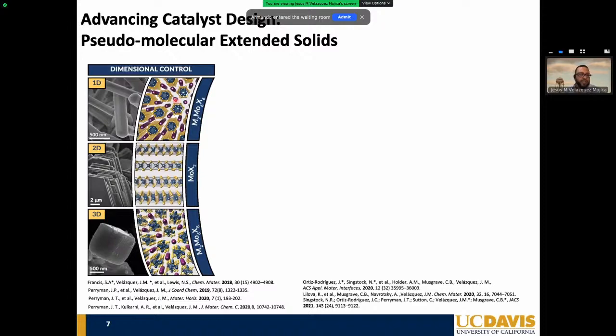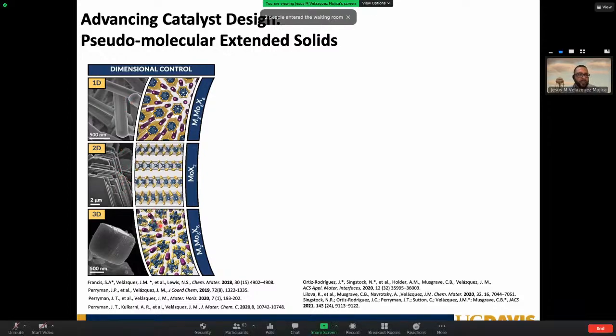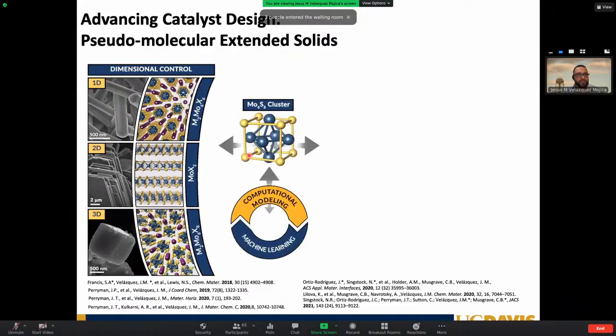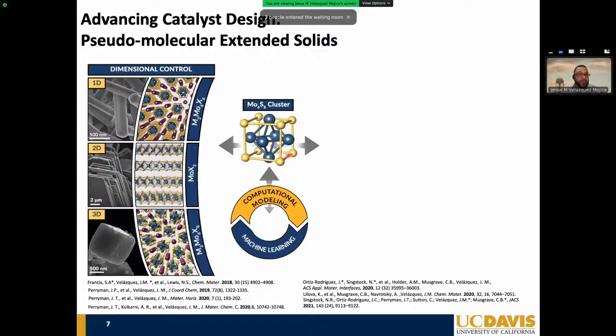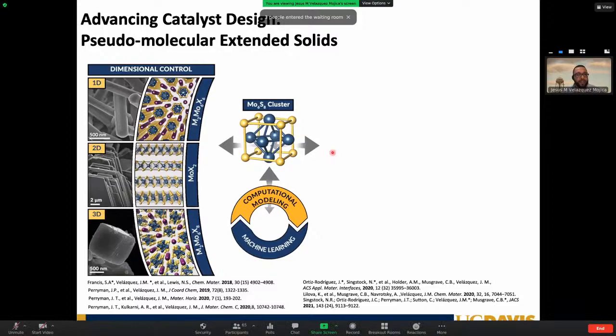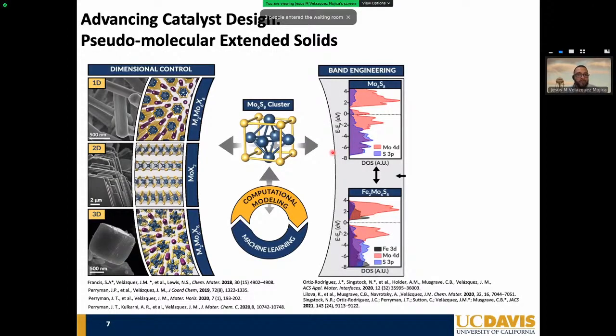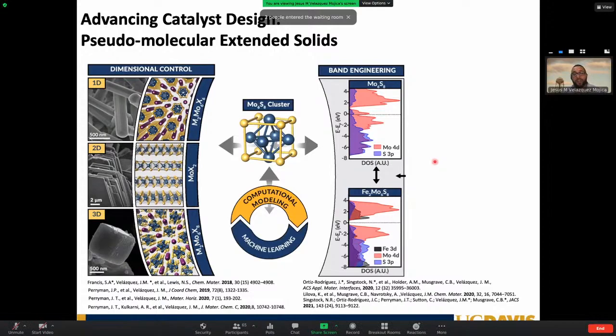And we've been able to successfully synthesize these materials to have either three-dimensional or one-dimensional coordination for electrocatalysis, but also we've been inspired, and you'll see why, by 2D materials, by metal chalcogenide 2D materials. We use chemical intuition, but we also use the computational power and the data science for us to be able to guide synthesis. And something really interesting that we've seen with these materials thus far, at least in theory, is that if we could play or fine tune the stoichiometry of the intercalant, we could actually have a shift of density of states and open up a gap and give us the opportunity to have an inherently active electrocatalyst that perhaps will have light absorption capability, and that will lead us to the world of photoelectrochemistry.